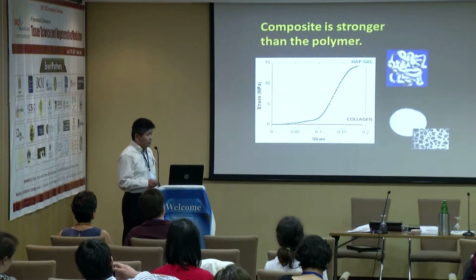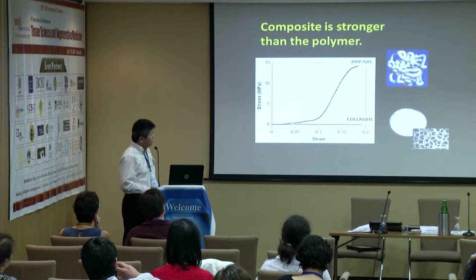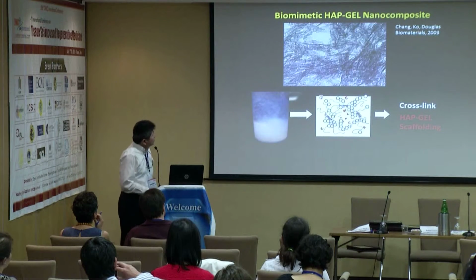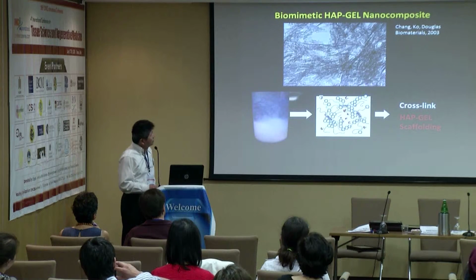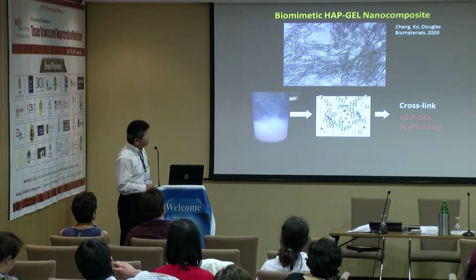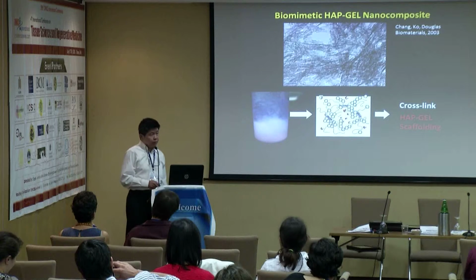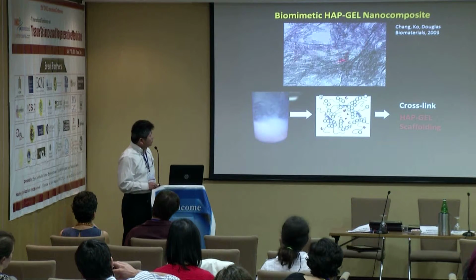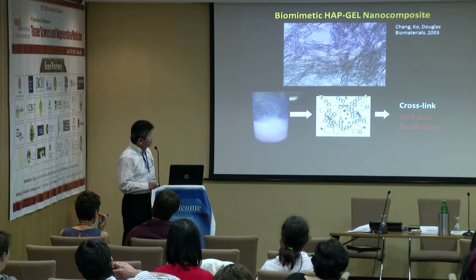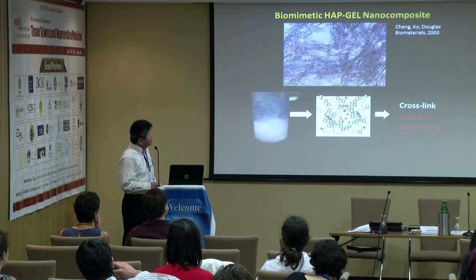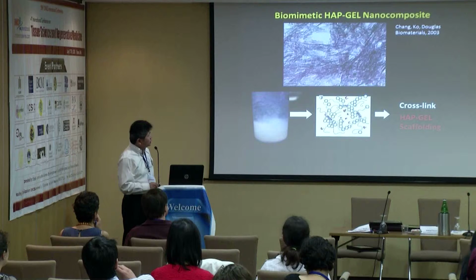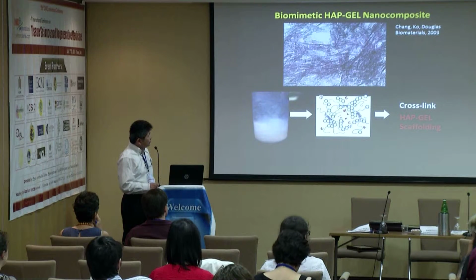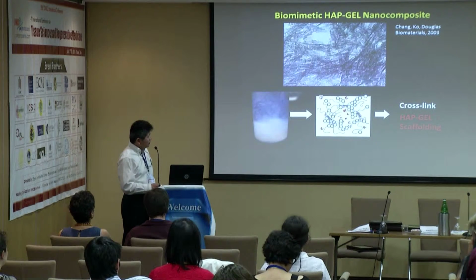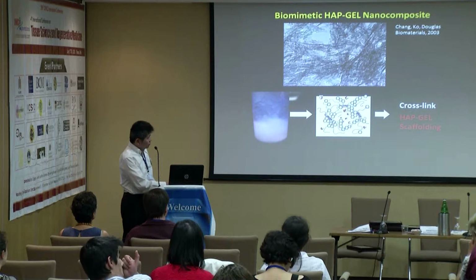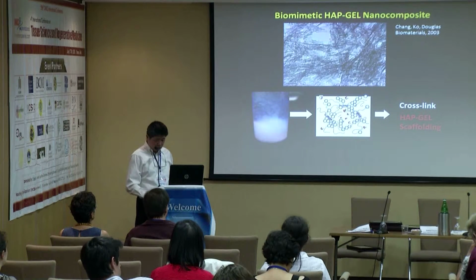Because skeletal bone functions as a mechanical supporting tissue, we would like the material to have this kind of mechanical property. More than 10 years ago, our group developed a biomimetic hydroxyapatite-gelatin nanocomposite using co-precipitation processing. The material allows us to create nanocrystal hydroxyapatite, which you can see as the dark parts. They form as a plate-like material on top of the gelatin matrix. By taking out the matrix, you can look at it by TEM. The schematic drawing of the material structure is like this: you can see the unstructured gelatin deposited with hydroxyapatite crystallites.